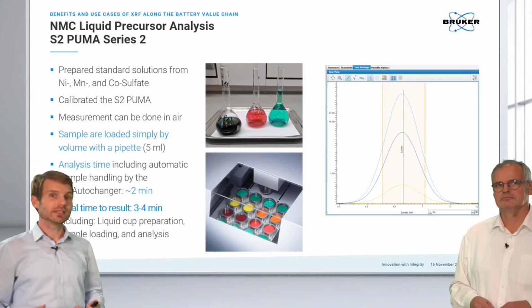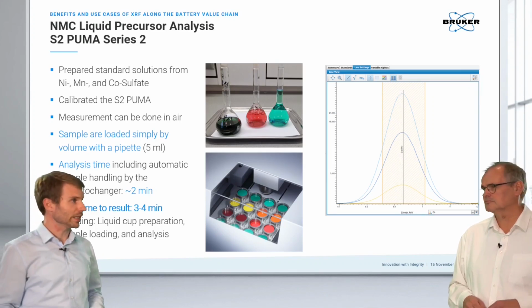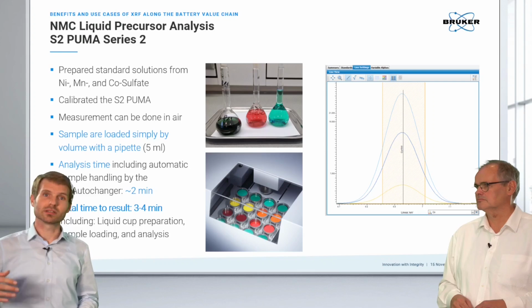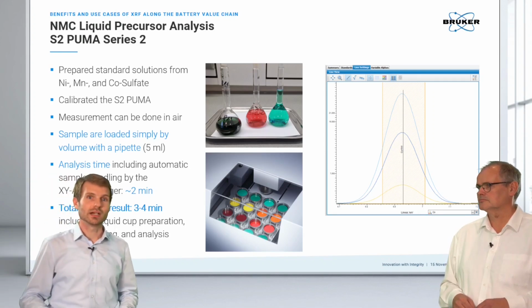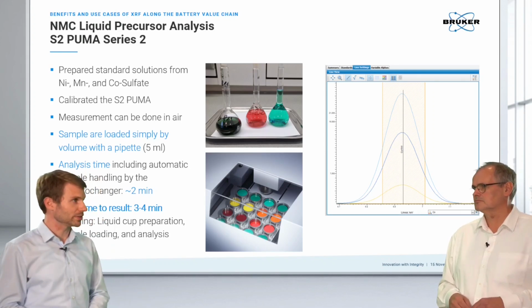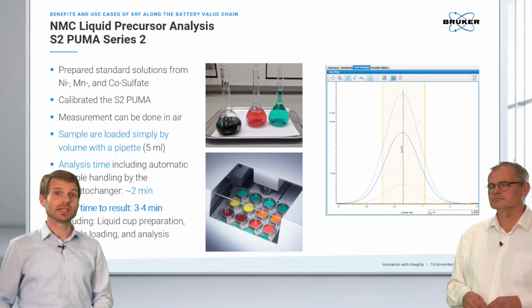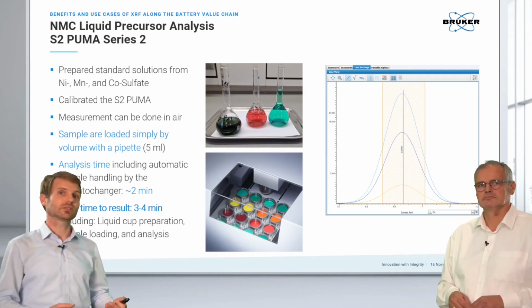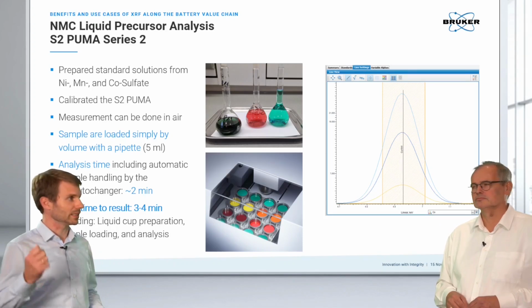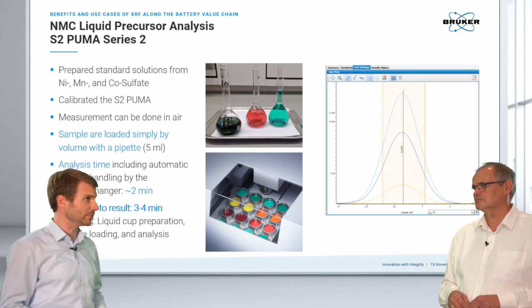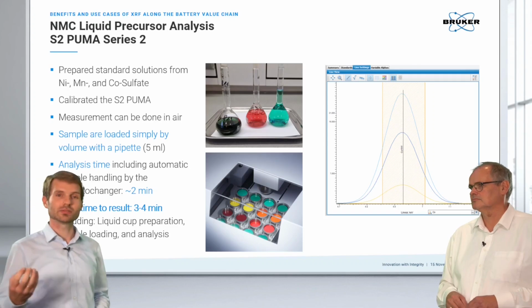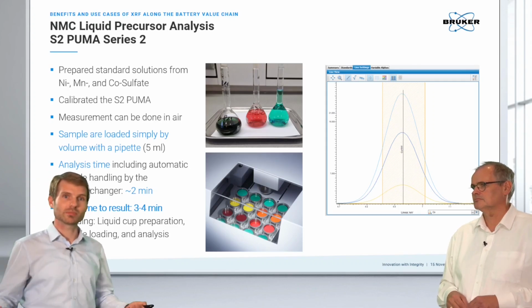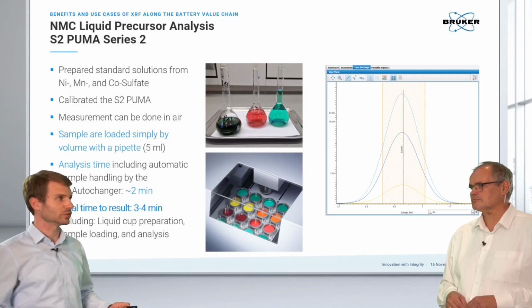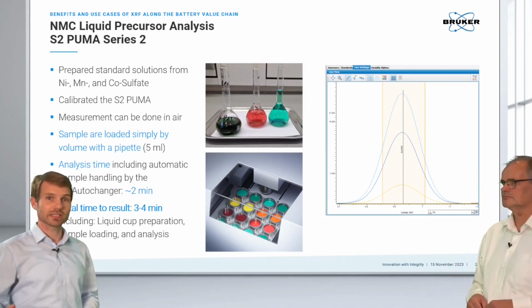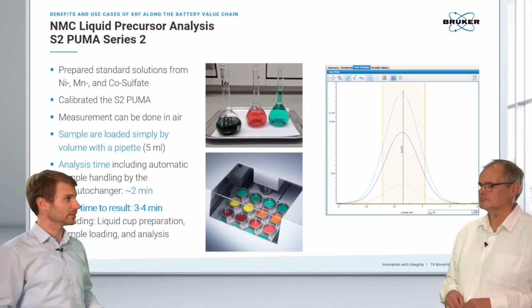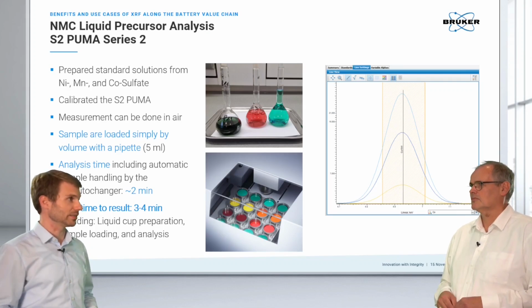So here you can easily produce a calibration based on nickel sulfate solutions on a system like our energy dispersive system, the S2 Puma. And then you can run your quality control checks by simply pipetting something like 5 milliliters into a liquid cup, and the measurement is done in 2 minutes. So preparation takes 1-2 minutes, measurement 2 minutes, 3 to 4 minutes, you're essentially done with your results.